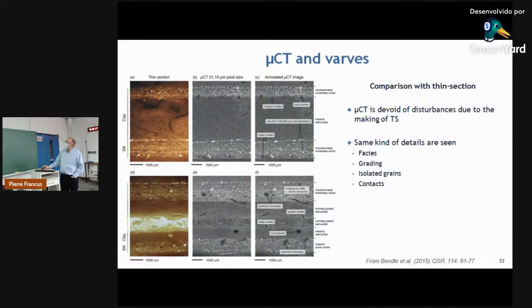And here is another exercise made by our colleagues from the UK. You have a thin section and the MicroCT image just nearby with a resolution of 21 microns. Basically, a resolution of 20 microns is equivalent to a picture taken at the petrographic microscope, because remember, the thin section has a thickness of between 20 and 30 microns. So you cannot really have a better resolution with the petrographic microscope.